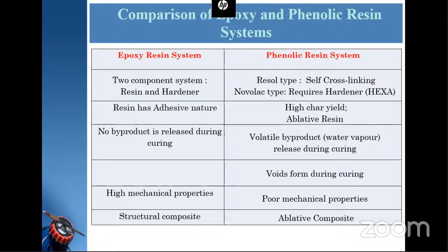Volatiles are released during the polymerization process as a byproduct. This has to be taken out by using a vacuum application. The equipment which we use for polymerization is called an autoclave, which has simultaneous heating and pressurization, and simultaneously we can vent out the byproducts by using a vacuum. Voids form during curing in phenolic resin, which we have to avoid by using the vacuum bagging technique.